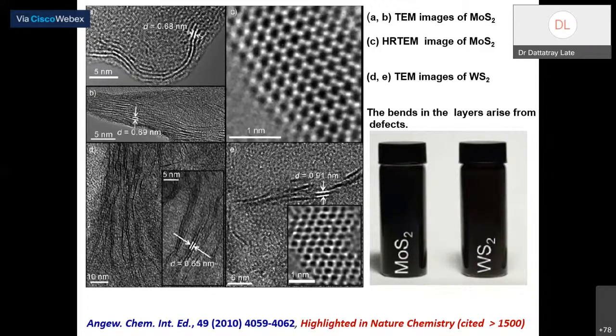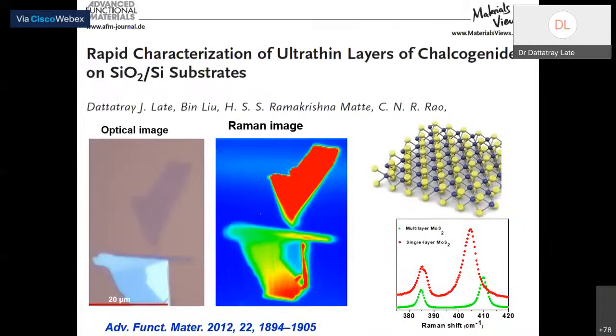Of course, we can characterize this material by using various other techniques like TEM, especially HRTEM. You can see the individual atoms under the transmission electron microscope. You can see the hexagonal structure of this MoS2 and WS2. So this clearly indicates that the things which we have obtained are monolayer, few layer in nature, having hexagonal structure. Okay, can you do it? Can you synthesize the similar material by the Scotch tape method, which I have shown you earlier? This material also can be obtained by simple exfoliation by the Scotch tape method.